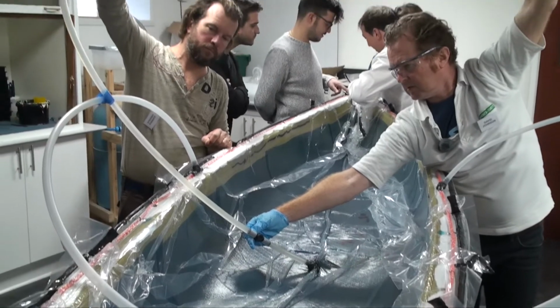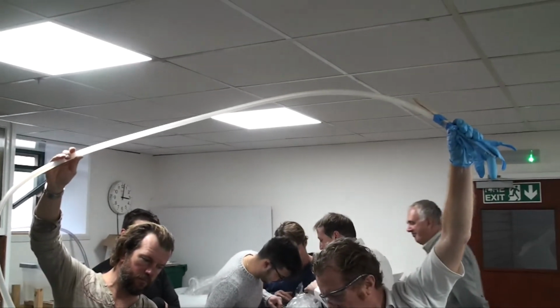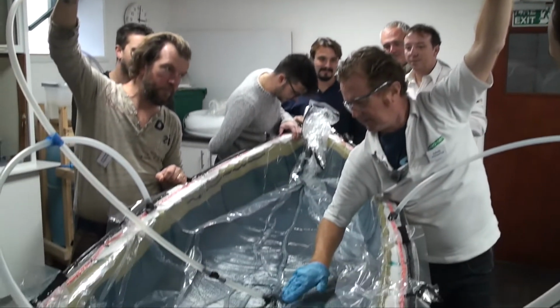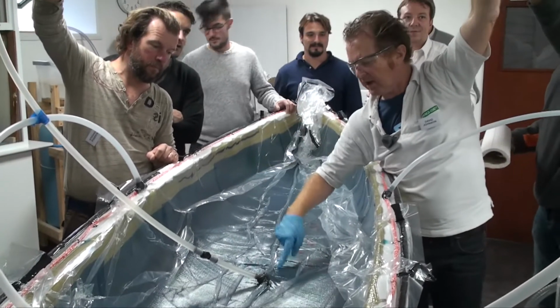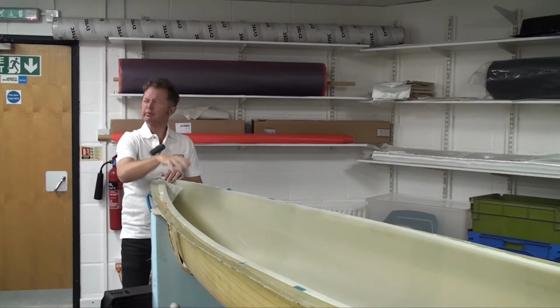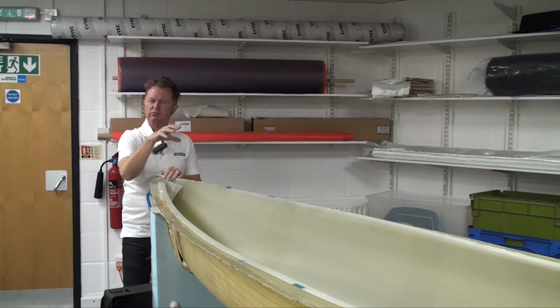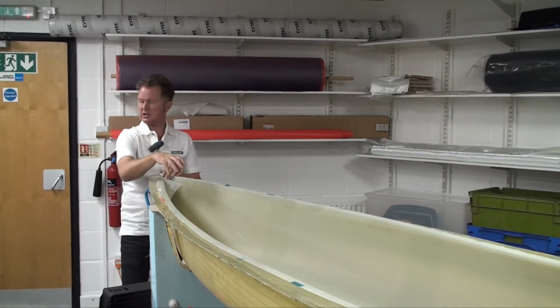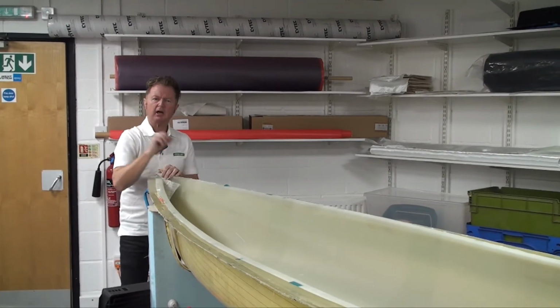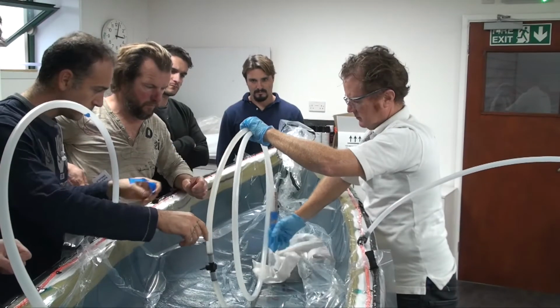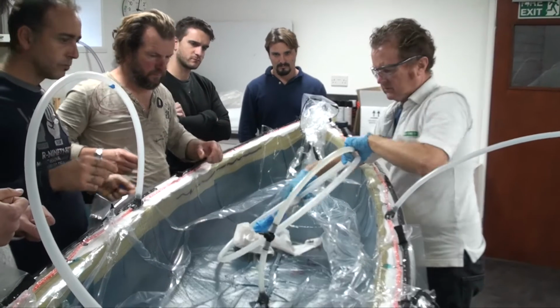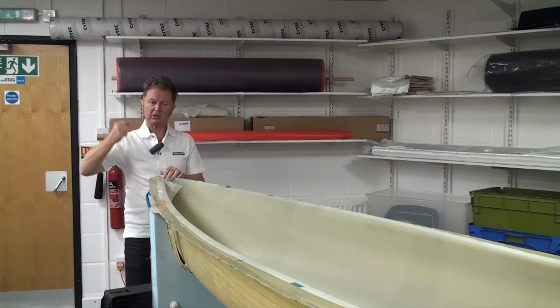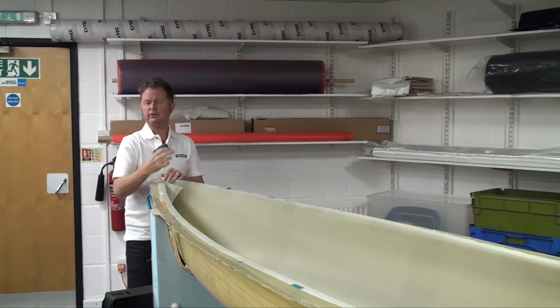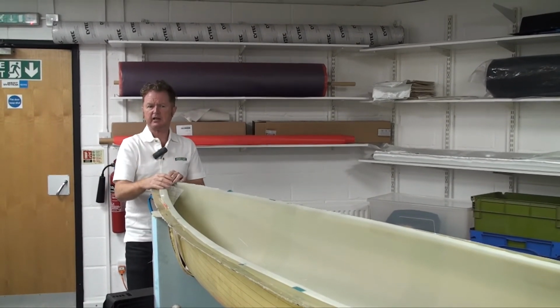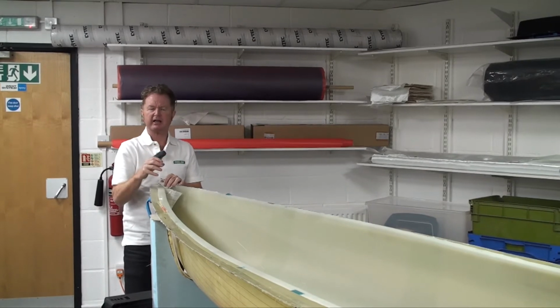Once the epoxy has reached the edge of the gunnel, the pipe is pulled from the reservoir and the last amount in the tube is driven into the mould. It's probably necessary to run the vacuum on a part such as this for a minimum of 2 hours. But on much larger parts, you'd want to draw the vacuum overnight to ensure you've purged all of the atmospheric air from inside the laminate stack.